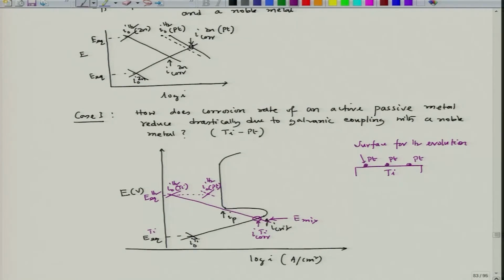So, now on the platinum surface it will have its own polarization plot, the cathodic polarization. If the polarization plot is going like this, let us say this is the point, let me shift it just to give a better explanation. So if I shift it here, now this will move like this. So this is the line, this is the hydrogen evolution on platinum surface, and this particular thing is hydrogen evolution on titanium surface.